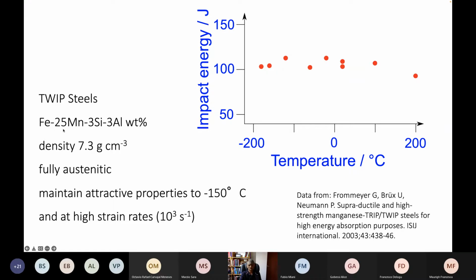So TWIP steel's typical composition is 25 manganese, 3 silicon, and 3 aluminium. If you only had the manganese and iron, you would still get it fully austenitic, but it would tend to undergo phase transformation to epsilon martensite as you deform. But with the addition of these further elements, there are various reasons for adding them, but one reason is that you remain fully austenitic as you deform. Because silicon and aluminium have low atomic weights, the overall density is reduced quite significantly. Normal iron has a density of about 7.8 grams per cubic centimeter. This is 7.3 grams per cubic centimeter, and it's fully austenitic and maintains its properties to cryogenic temperatures.